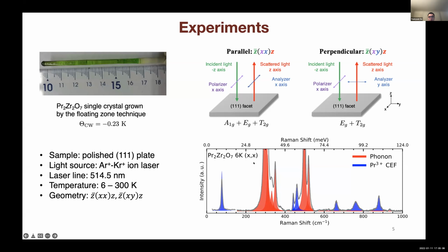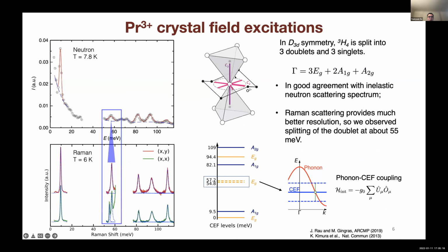This is the Raman spectrum we took at about 6 Kelvin. Red peaks are phonons and blue peaks are crystal field excitations. And in this talk, I will only focus on the crystal field excitations. Ideally, the praseodymium ion is surrounded by 8 oxygens, forming this local environment. And the 3H4 manifold is expected to be split into 3 doublets and 3 singlets.